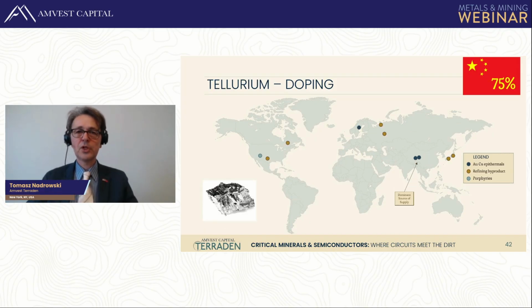Another doping material, tellurium. Tellurium usually comes as a byproduct of electrolytic copper production, but there are also dedicated mines to tellurium. And again, you won't be surprised to find out that there are in China and Sichuan. Otherwise, you have to look for epithermals with gold and maybe volcano. The VMS deposits with copper. This doping material is mostly for the indium gallium arsenide substrate rather than for silicon, and it enhances conductivity as the doping ions usually do.